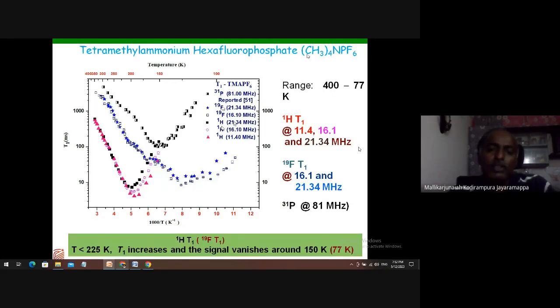For hydrogen, I made this measurement at 3 frequencies. As you can see, these are the magenta triangles, open circles, and filled squares. All of them are for proton NMR. As you can see, at high temperature, what frequency you are making measurements at does not matter. What matters is below this temperature, wherever we get this minimum; from that point onwards, the behavior depends on what frequency I made this measurement at.